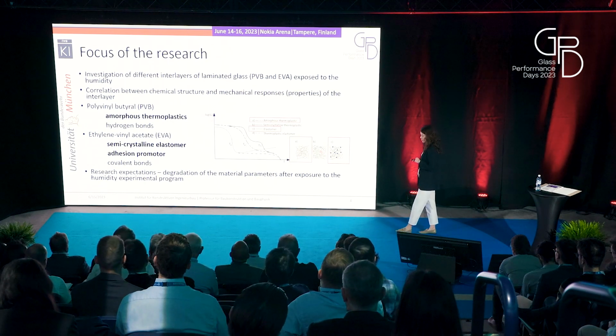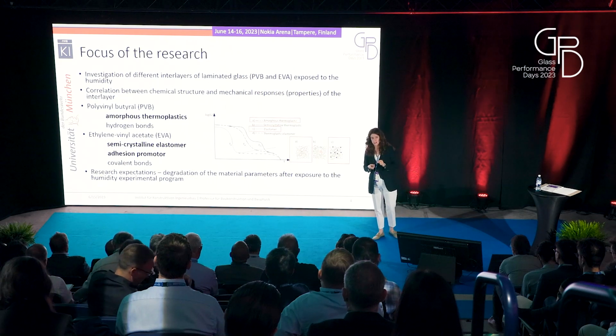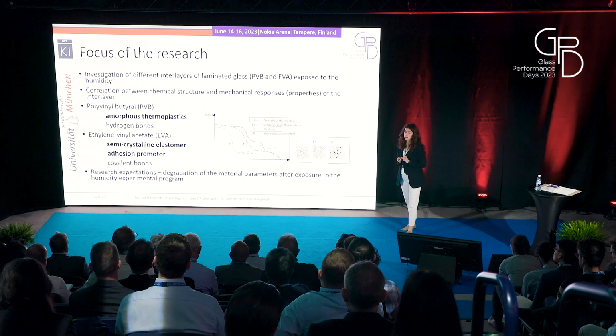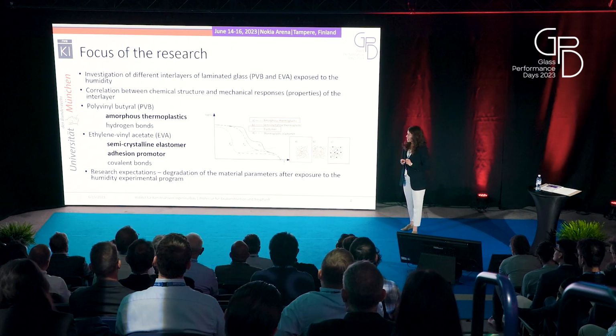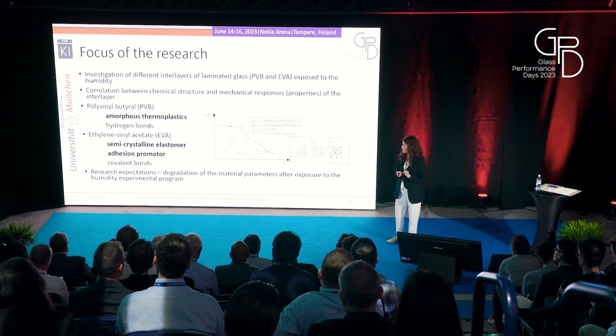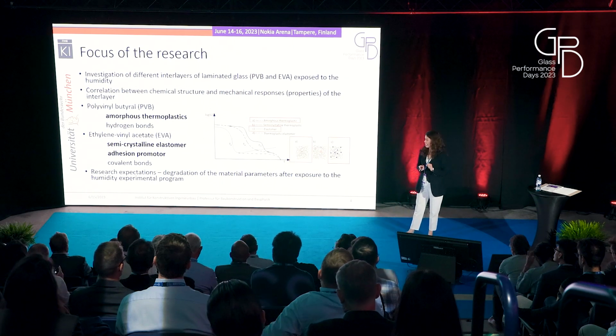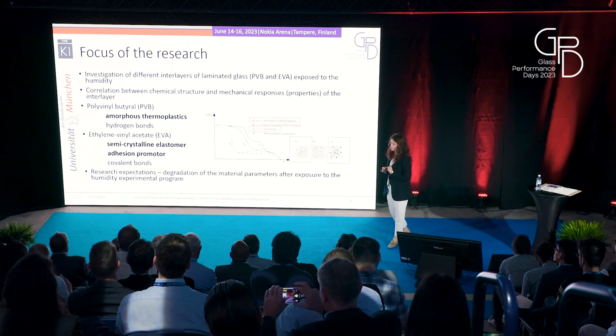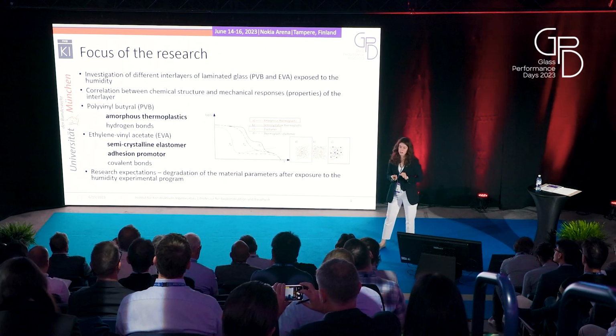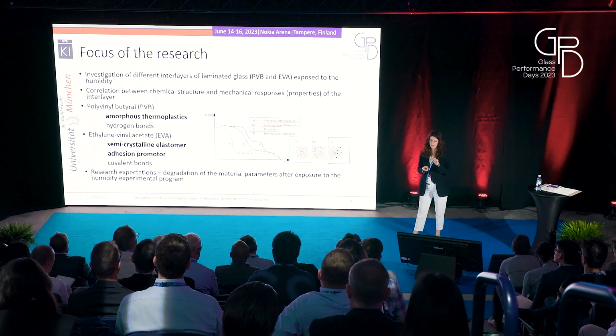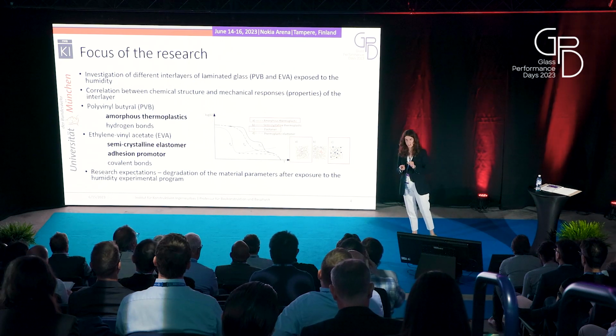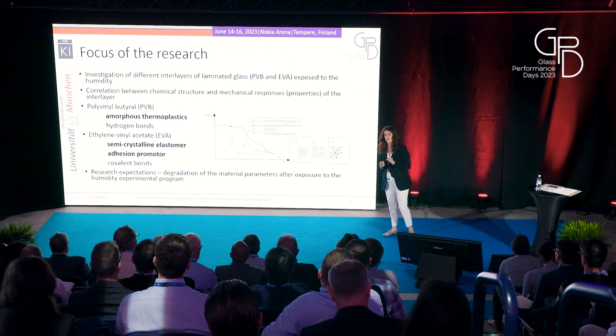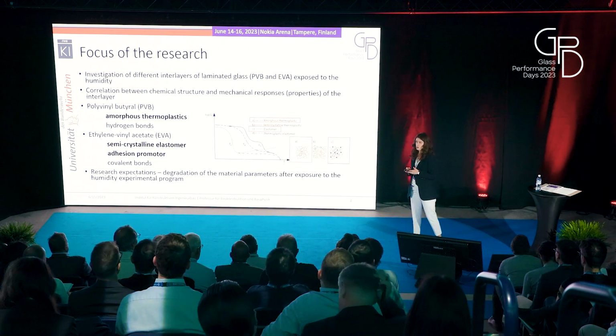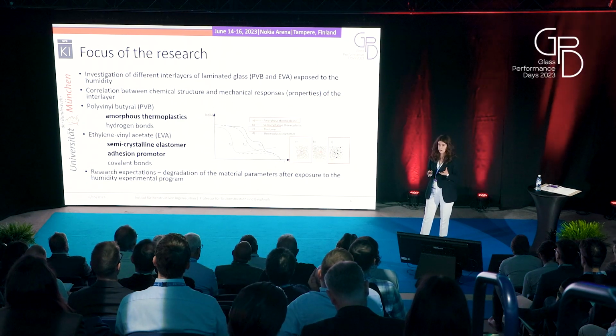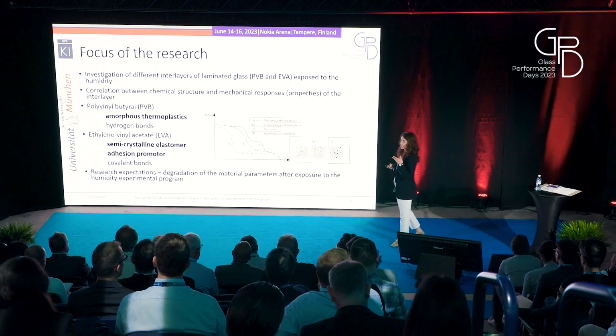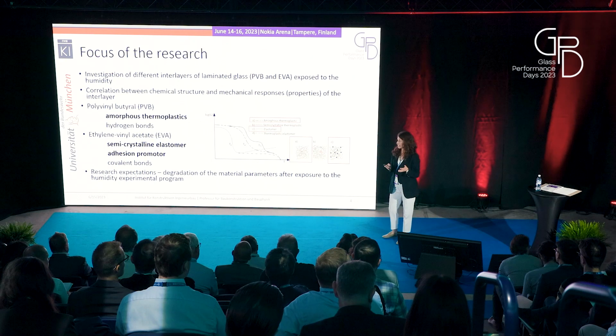The second big difference is the type of chemical bonds which are created between the interlayer and the glass during the lamination process. During the lamination of the glass and the PVB, the bonds which are created are hydrogen bonds. These hydrogen bonds belong to weak chemical bonds. What does that mean? It means that if, in a chemical equation, we add water, those bonds will break. An example from reality: we have laminated glass somewhere outside, exposed to a higher level of humidity, or it's just a rainy day. So we have additional water entering the chemical equation, which breaks that bond, and that's actually the delamination.